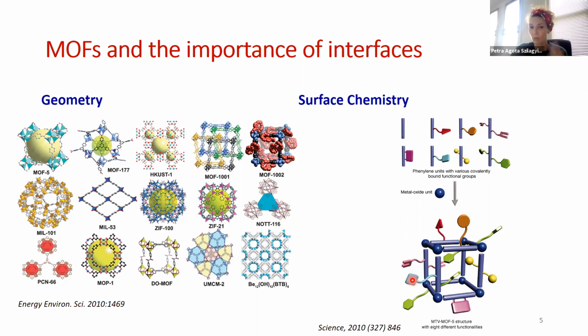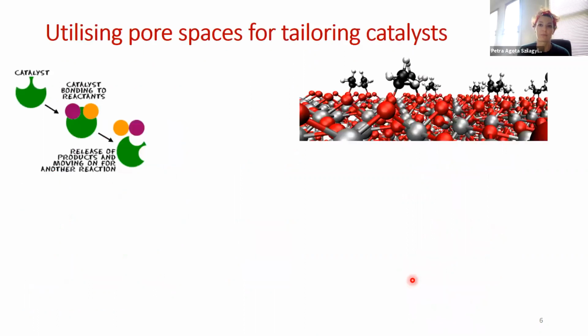of these clusters. One more important thing I would like to point out is that the typical pore size of metal organic frameworks is between 0.5 and 3 nanometers. So it's really at the lower scale of nanoparticles and the higher end of nanoclusters we're talking about. And I did mention that today I would be talking about how these can be used for catalysis. And of course, metal organic frameworks are solids, so we are interested, obviously, in heterogeneous catalysis. And as such, the surface is really important. And as I already mentioned, these metal organic frameworks are really highly porous. So they have surface areas of thousands of square meters per gram. And also, obviously, the pores themselves are very many and, once again, basically identical in shape and size.